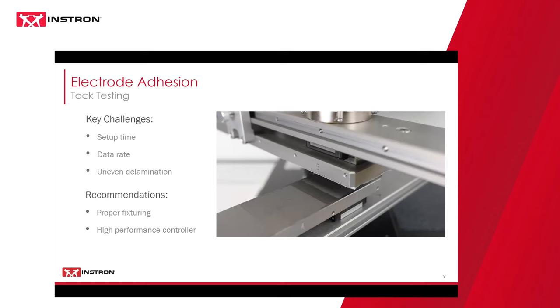And then lastly with tack testing, one of the challenges is uneven delamination. It's something that I've seen before in tacks that can lead to widespread variability in your results. This occurs when the platens are not properly parallel to one another. It can change every time the fixturing is replaced, or after each test, if the proper fixturing isn't used. So the tack fixturing, the one to the right here, utilizes what we call a spherical seat. This is one way to ensure proper parallelism between each test, where you lock the spherical seat, and it will maintain that parallelism throughout the test.